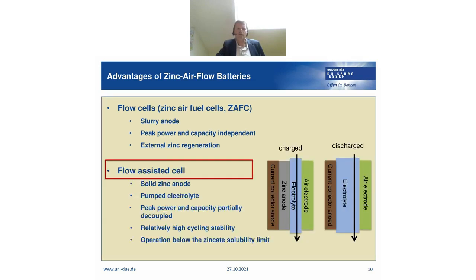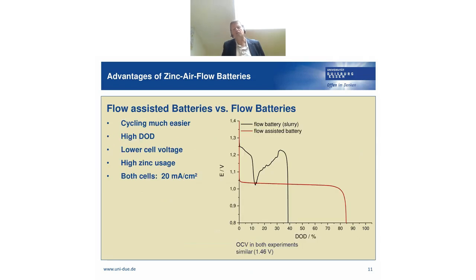I want to compare it first with a flow-assisted cell, which is a little bit similar, but has a solid zinc anode. We can see it here on the picture on the left in a charged state. So we have the current collector, the solid zinc electrode, then the electrolyte and the air electrode. For flow-assisted cells, we need a lot of electrolyte, which is pumped through the cell to dissolve all the zincate that is produced. In the discharged state, all the solid zinc anode is gone, and all the zinc is in the electrolyte as zincate. So there's an advantage: we have a relatively high cycling stability with this kind of system, but this operates, of course, below the zincate solubility limit.